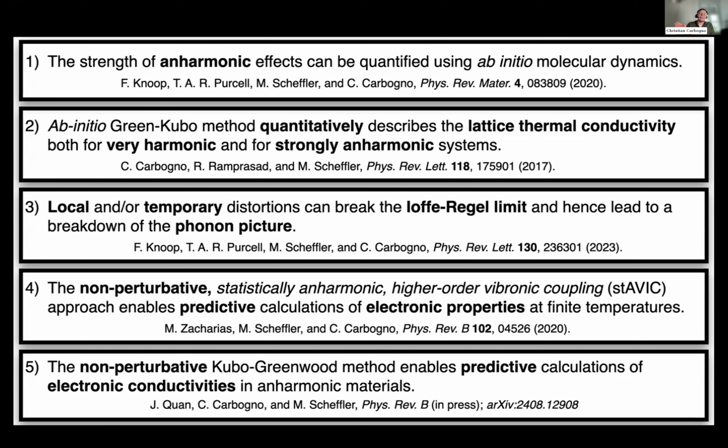So you add this up as 1 over kappa complete is 1 over kappa EE, plus PP, plus EP. Typically or often this is good enough. If you would really like to do something more involved, this would imply going to non-adiabatic systems, really doing explicit electron dynamics and nuclear dynamics, and that can become expensive for everything that is not a toy system.